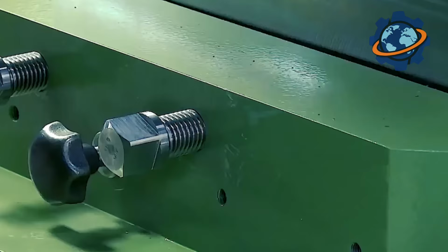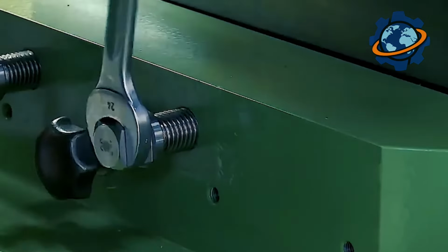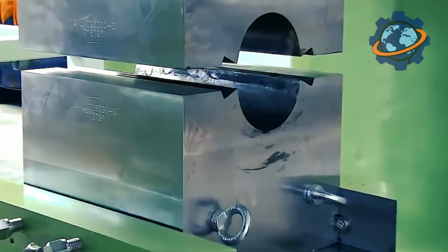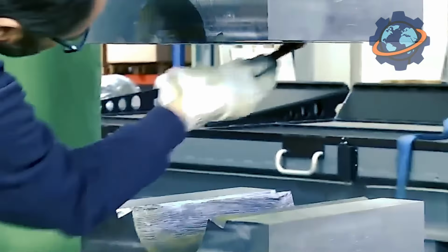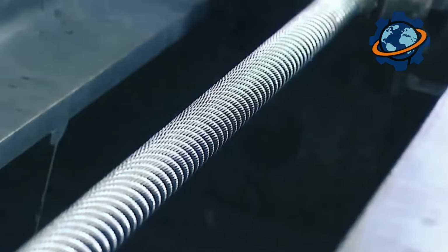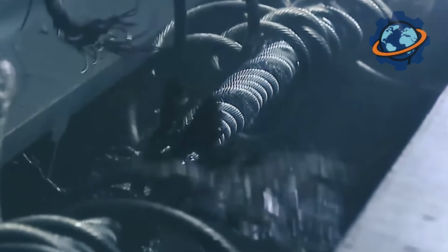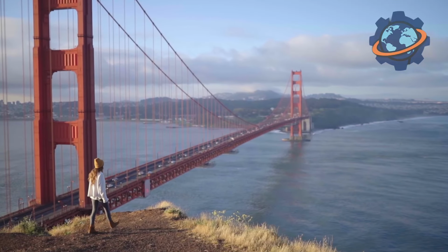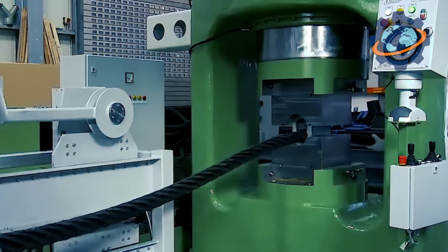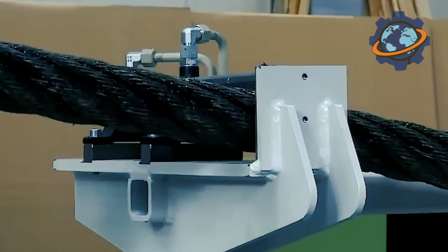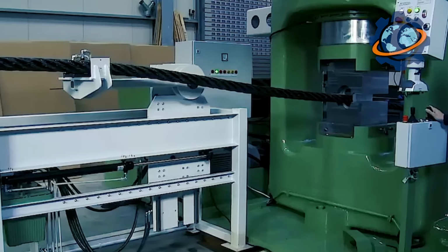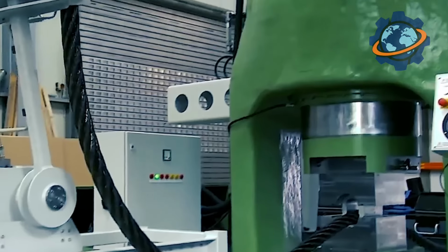A portion of the batch is selected for mechanical testing. The wire is clamped in hydraulic jaws and pulled until it breaks. This determines its tensile strength and breaking load. If the wire holds up, it's ready for work at heights of hundreds of feet, supporting the weight of a car bridge. The surface is checked separately for microcracks, burrs, corrosion. High-resolution cameras or even eddy current testing are used here, which can see beneath the top layer of metal.